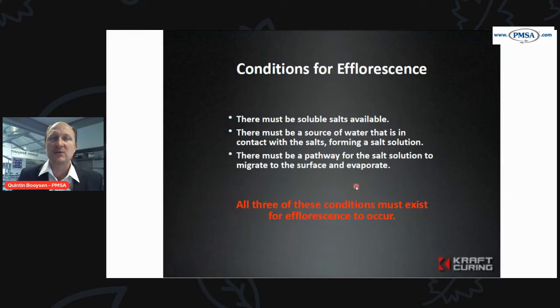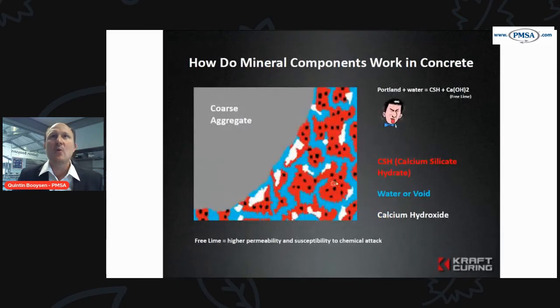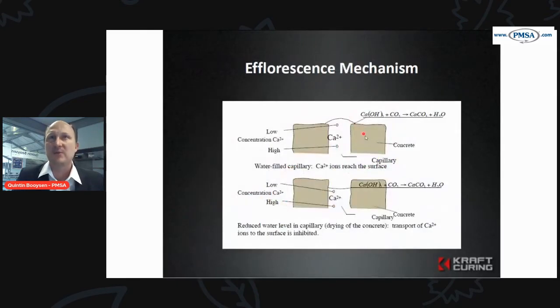So the water evaporates, you're left with this calcium hydroxide on the surface, which together, I'll go to another one. Here's a bit of a better presence. It comes on the surface of the concrete, and that together with carbon dioxide will form your calcium carbonate. And the water would evaporate off, and you're left with this unsightly white formation, which effectively is a type of limestone, a calcium carbonate.